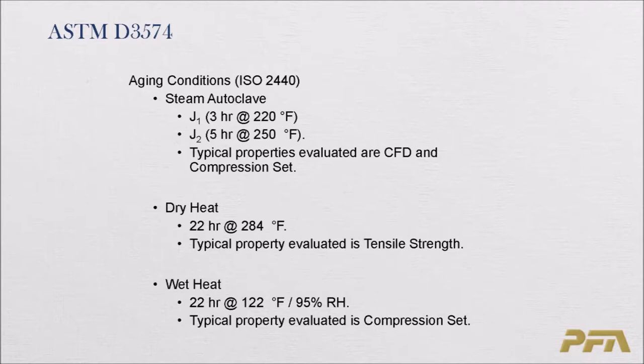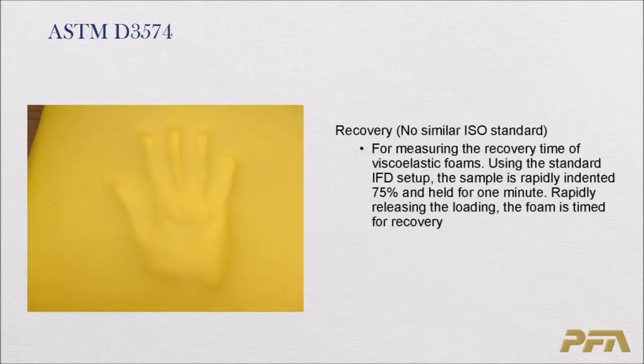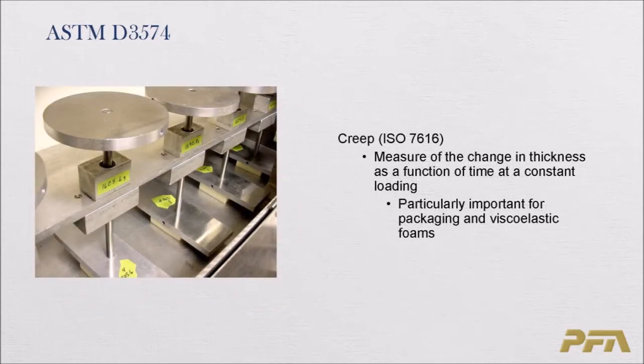The recovery test is for viscoelastic foam. Similar to the IFD setup, the sample is rapidly indented to 75% and held for one minute, then rapidly released, and the foam is timed for recovery. Finally, there is a creep test — a measure of the change in thickness as a function of time at constant loading, particularly important for packaging and viscoelastic foam.